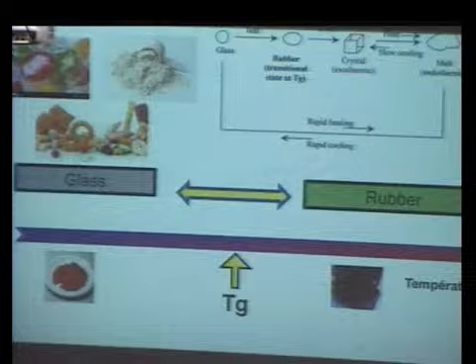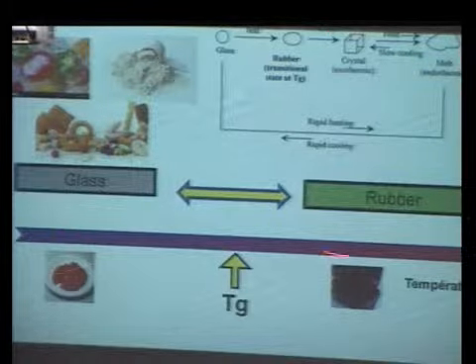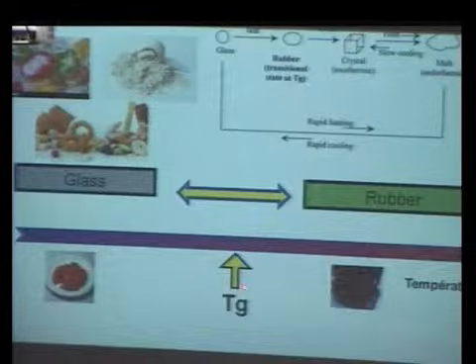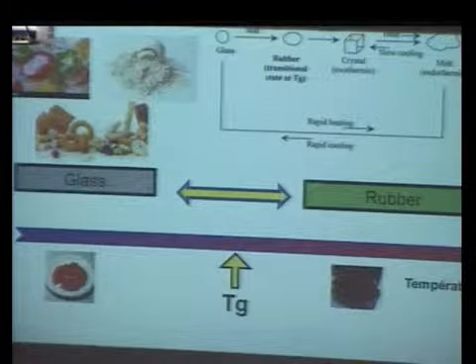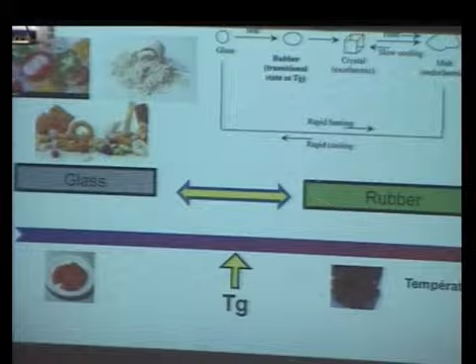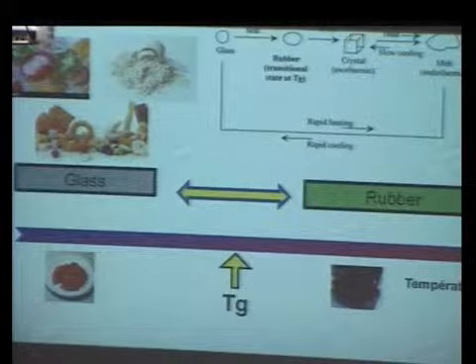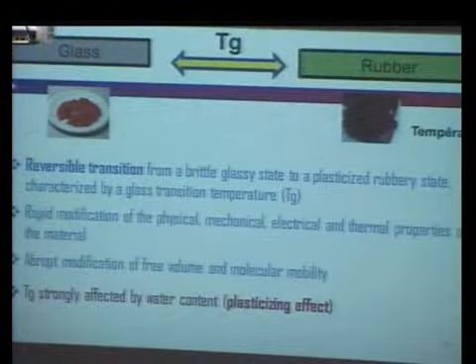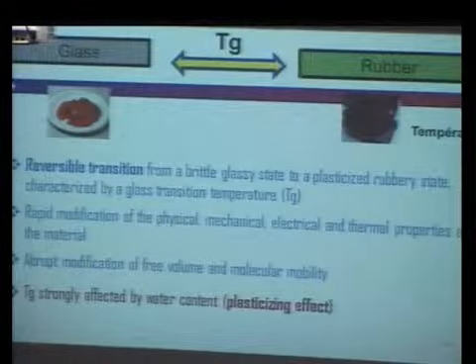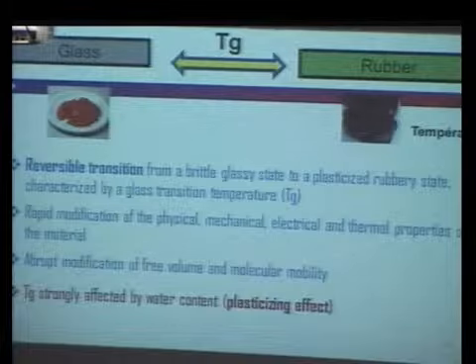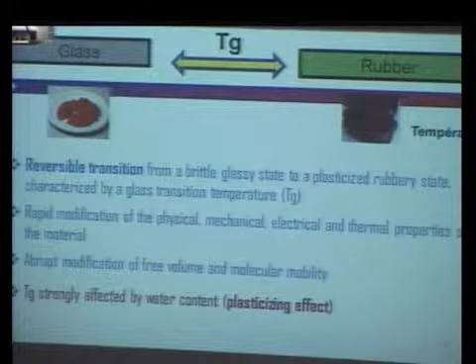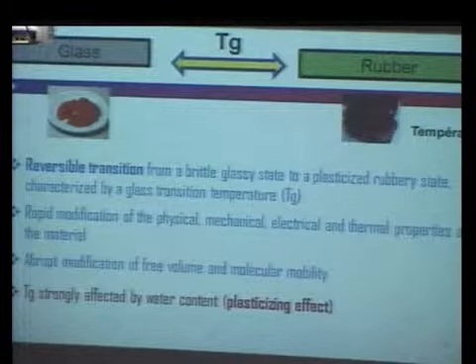The crispness of your product is in danger because the glass transition temperature can go under the storage temperature. That's why you can have glass transition in a lot of products if you don't take care of water and if you don't protect them. So in a few words, the glass transition is a reversible transition. There is no heat absorption or desorption. It's a transition of the second order.